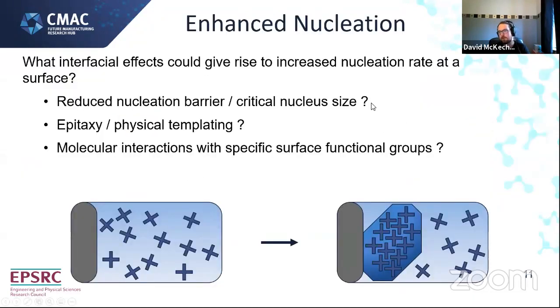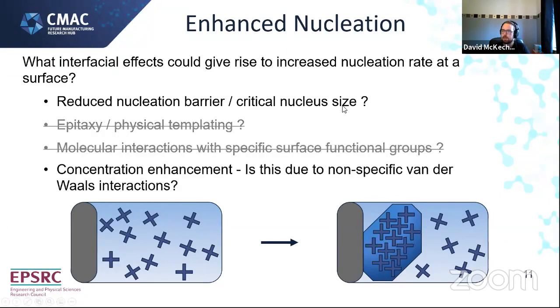Returning to the question of enhanced nucleation, the reduced nucleation barrier from classical theory likely still plays a role, but epitaxy and specific molecular interactions don't seem significant here. Instead, our simulations suggest concentration enhancement at the interface driven by non-specific van der Waals interactions between the interface as a whole and the solute molecules within the solution.